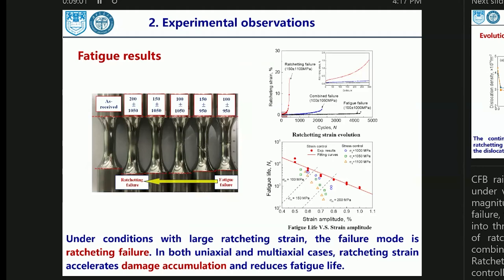And these are the fatigue results of the experiment. We can see that with failure strength increase, the failure modes can be divided into three types: maybe the ratcheting dominant failure ones, the fatigue dominant failure ones, and the combined one. So the ratcheting strain is maybe important to the fatigue life. And if we put all the strain controlled or stress controlled fatigue results into one figure, we can find that all the stress controlled life is less than the strain controlled ones. And as the mean stress and stress amplitude increase, the effect of the ratcheting strain is more obvious.